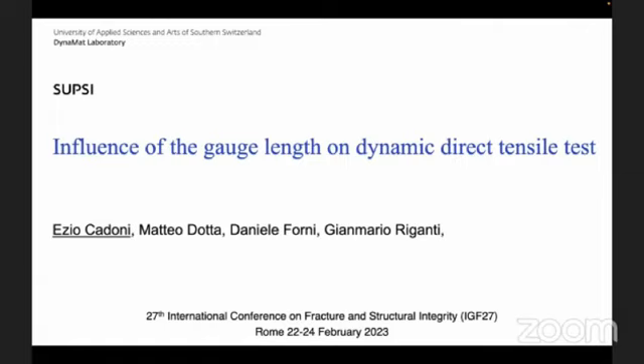The Kolsky bar or split Hopkinson bar is universally recognized as the most appropriate method to study material behavior in the strain rate range of 100 up to 1000 strain per second. The dynamic equilibrium is an essential requirement that has to be met in order to ensure a uniform state of stress and strain across the specimen. Three round trips in the specimen are generally accepted as the necessary amount of time to reach this state.